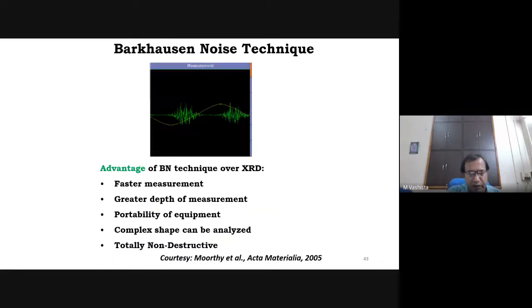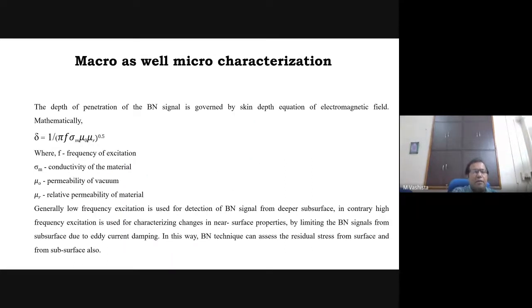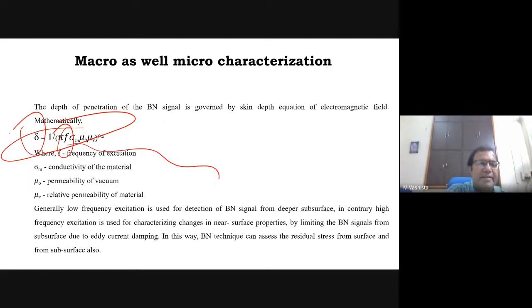On the other hand, the Barkhausen noise technique provides faster measurement, portability of equipment is there, and this is eco-friendly because only a magnetic field is used, and a magnetic field is not harmful for the operator or the user who is using this Barkhausen noise analyzer. We can change the depth of measurement. How can we change it? Because the depth of penetration of the magnetic field is governed by this mathematical expression. In this expression, only the magnetic frequency is there. So by using this magnetic frequency, I can change the depth of penetration as per my requirement. I can increase the magnetic frequency or I can decrease it. By increasing and decreasing the magnetic frequency, I can change the depth of penetration.